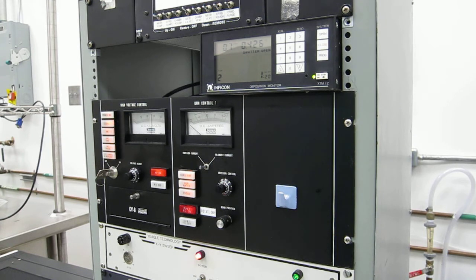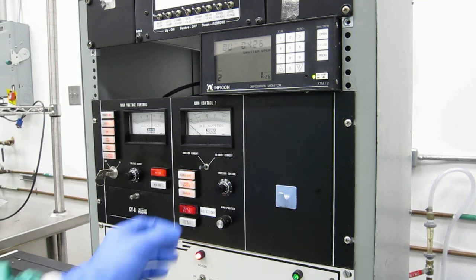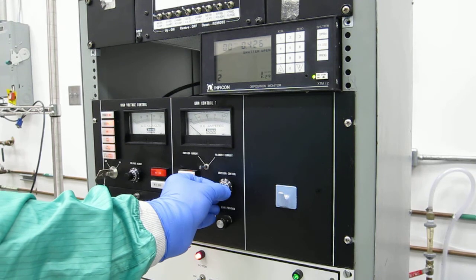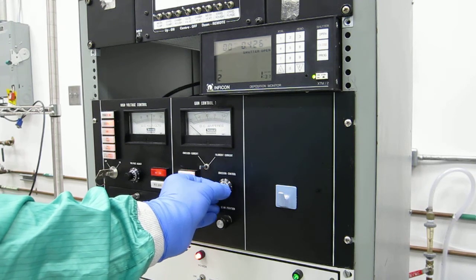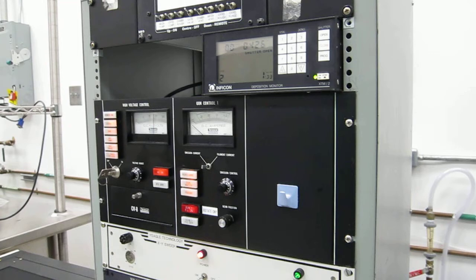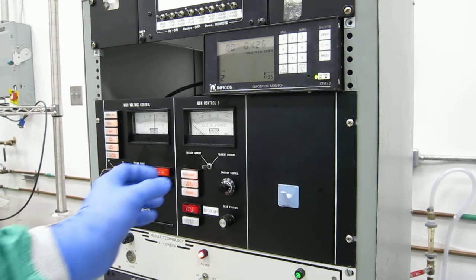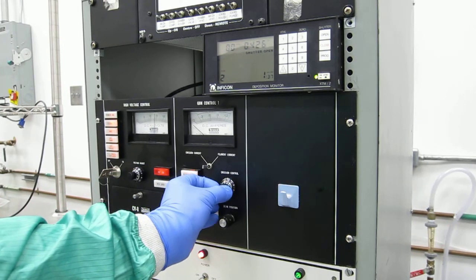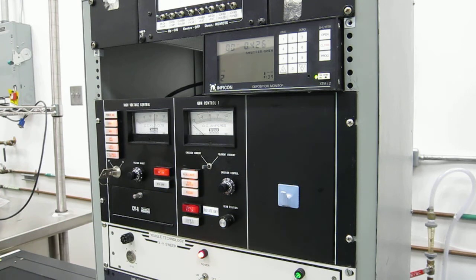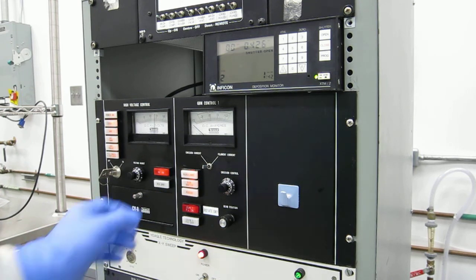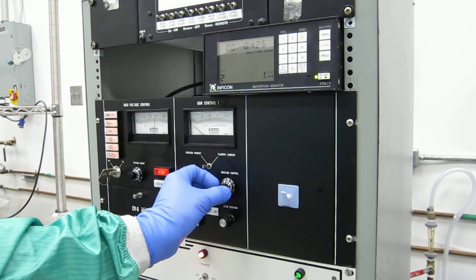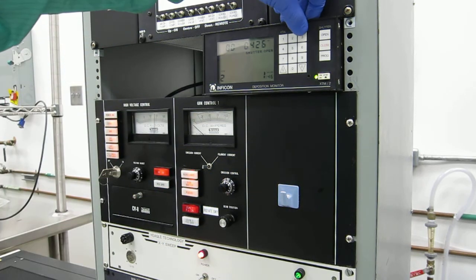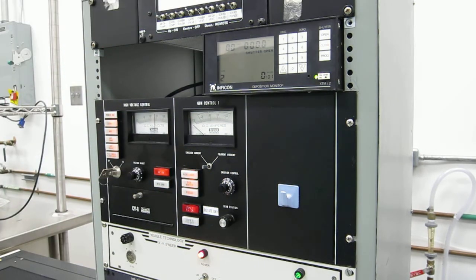With the electron beam now hitting the crucible and heating up the material inside, it's time to begin our deposition. We increase the current to the source until the source is glowing orange, at which point we can rest assured that our material is now melted and deposition could proceed. Like any other type of deposition, zero the meter and open the shutter to begin.